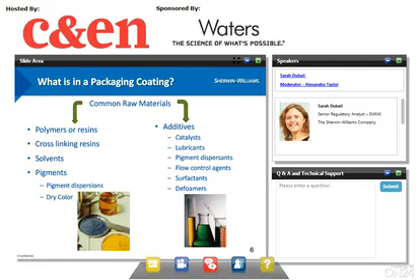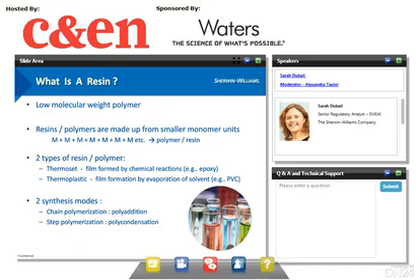The solvents are the carrier for the resin. They must be compatible with the resin, and they will influence viscosity, solids, and at the end, application properties. The coatings are then cured. The solvents will be removed from the final film. The coating can be functional or decorative, or both. Therefore, it can be clear, dyed, or pigmented. And pigments will add color to the coatings. The most common one is TiO2. Then additives. Additives are chemicals of various nature. They are added to enhance coating features like the catalysts or the lubricants, or they provide more robust application like the defoamers.